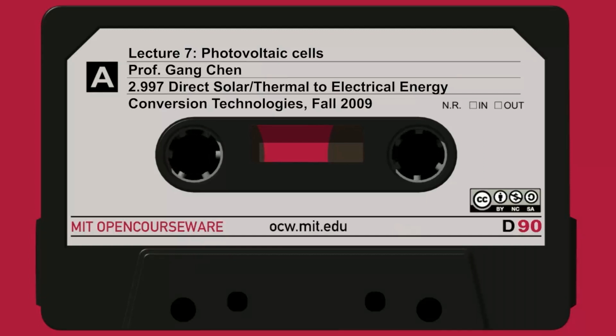So that's the absorption. And that's why some use materials like copper indium gallium selenide. They have a very sharp rise, 10 to the 5 per centimeter. So if you have 10 to the 4 inverse centimeters, that gives you 1 micron. So if you want to use thin film, a direct gap is a good one. Those are good with thin film. And that's why when people make amorphous silicon thin film, it's pretty good here. This is useless here.